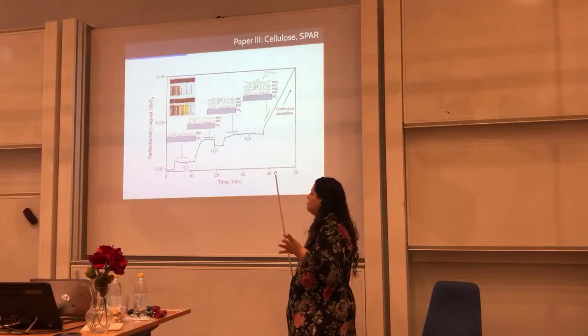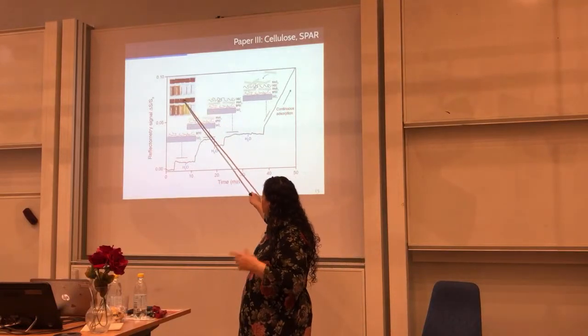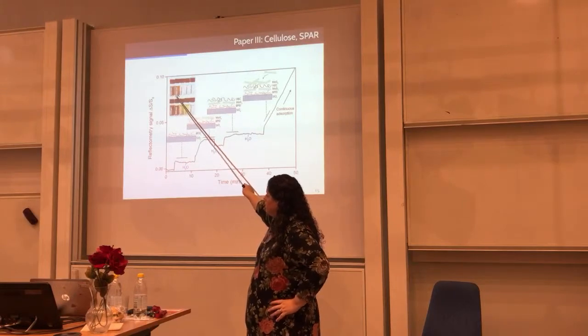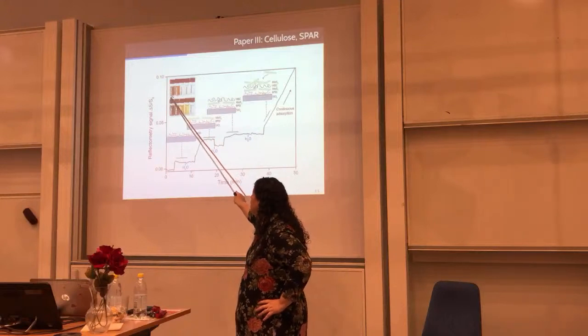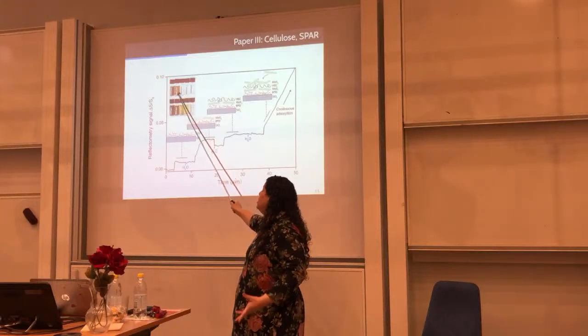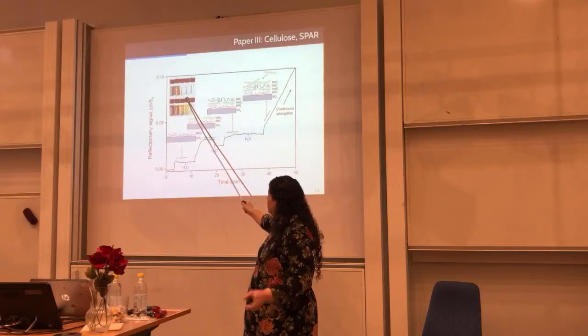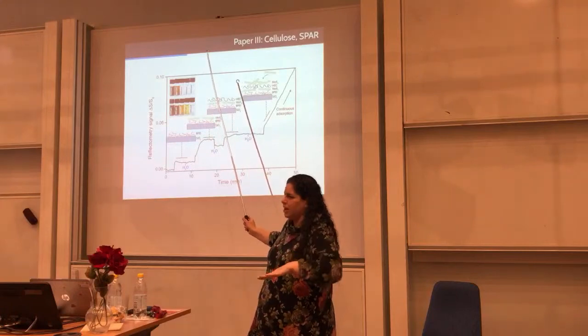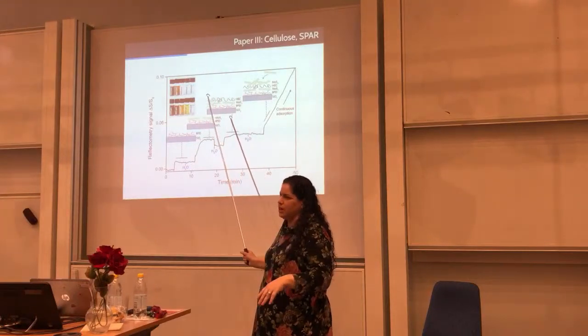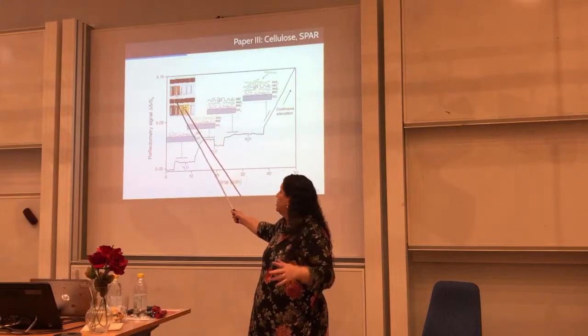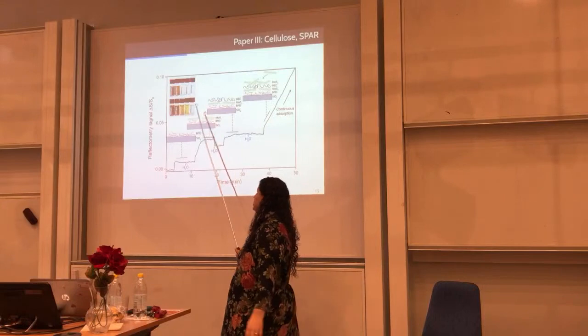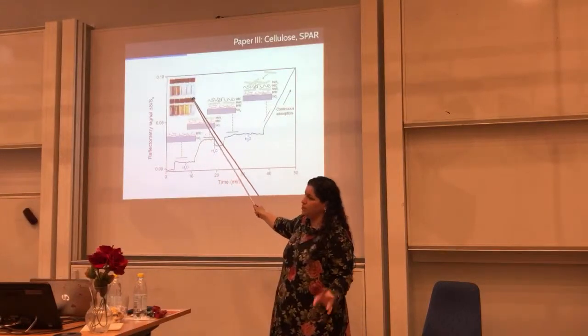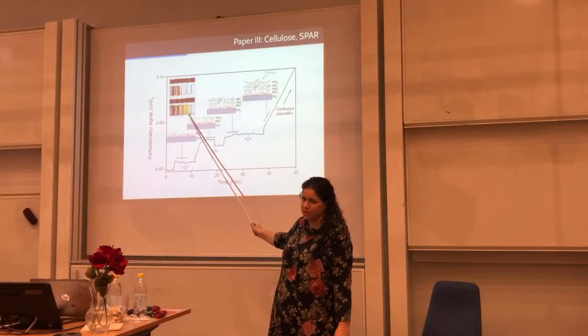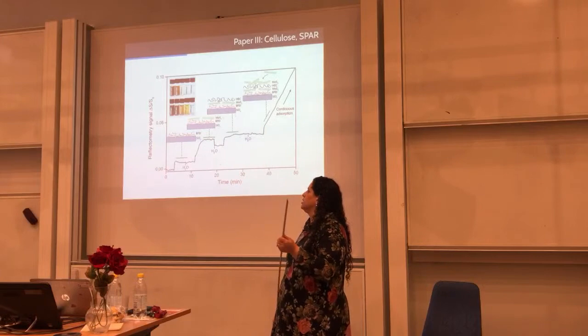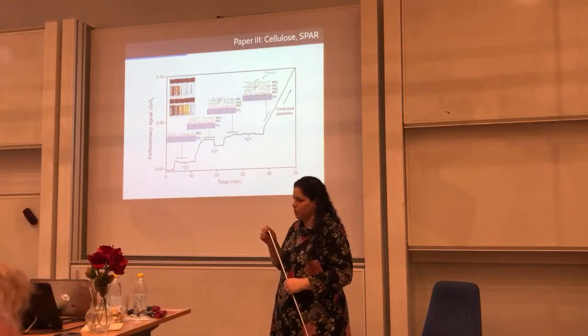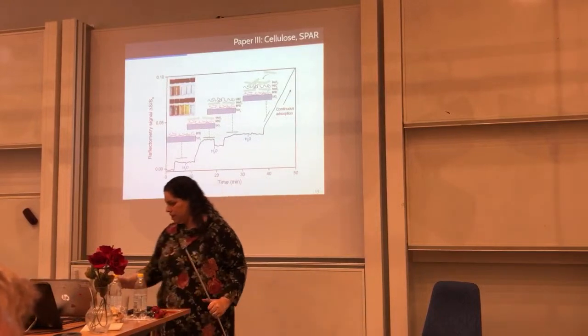and this explains why these dispersions were so good, stable. So these dispersions are illustrated here. Here I have the dispersion of exfoliated molybdenum sulfide in water without any stabilizer. When I'm varying the centrifugation speed, I'm simulating a concentration decay rate, let's say, because the higher the speed, the fewer particles there will be in the water, so the concentration will reduce. And then you see that it becomes white quite fast here, but here you still have particles dispersed. So that proves how well this system is working and how well HEC can stabilize molybdenum in water. And this is a great finding for this paper.